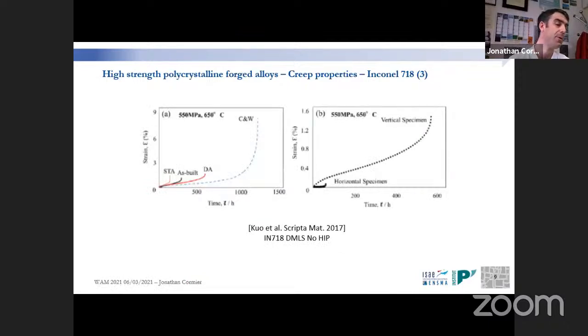That's something which has already been observed 4 years ago by a Japanese team in the group of Koji Kakehi at Tokyo Tech, where they compared the creep properties of vertical and horizontal specimens. I forgot to mention the results we obtained within the framework of the thesis. We had a little bit of anisotropy, but the trend was almost the same for both vertical and horizontal specimens.